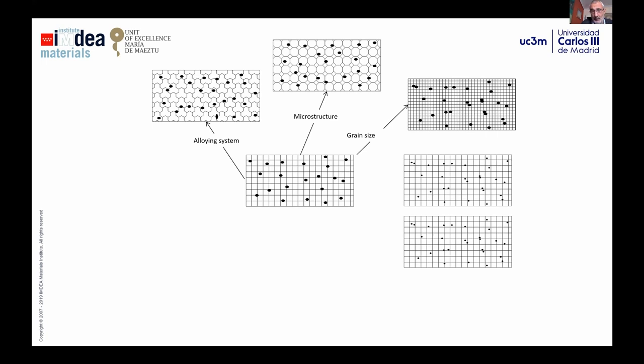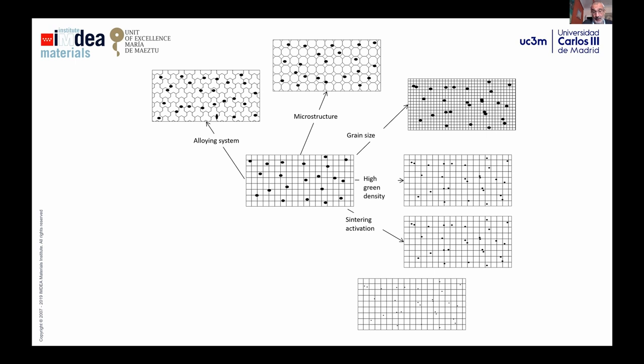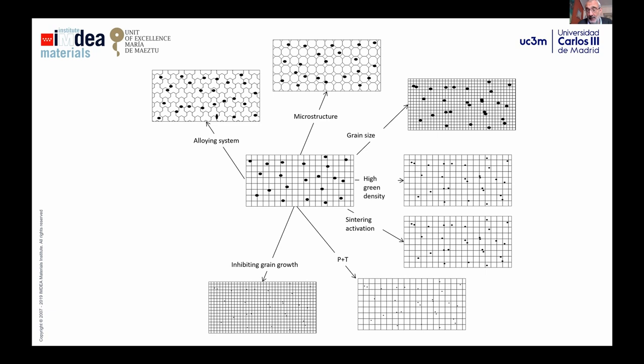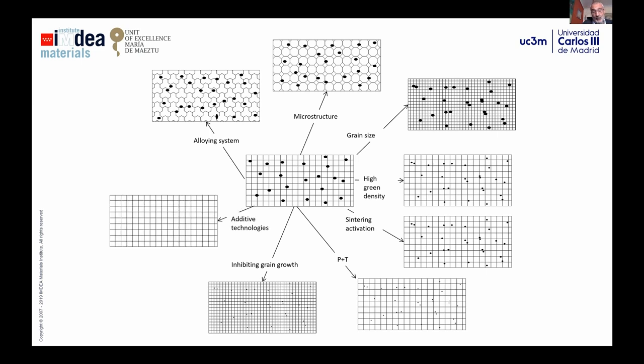But also with powder metallurgy, through high green density or by sintering activation, you can reach near full density materials. Here I can draw some porosity, but this porosity is really, really small. Sometimes it's difficult to detect by a lot of characterization methods. Of course, you can apply pressure and temperature. You can inhibit the grain growth with methods, as I mentioned, like microwave sintering or spark plasma sintering. And today we have a last way to obtain full dense material with additive technology.